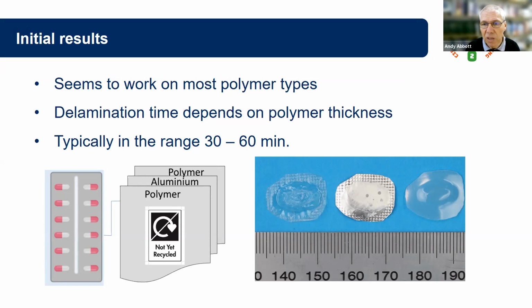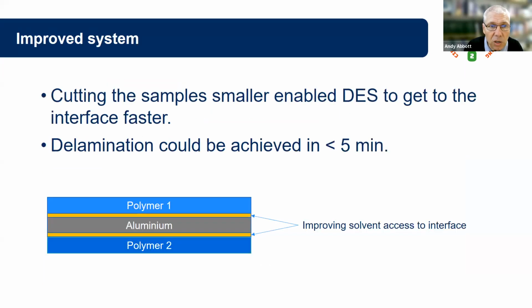We've got a very nice picture on the bottom right of your screen of, I think, a 3-layer multi-package system. Again, this is a blister package that was used for tablets. You can see quite clearly that we've got 3 nice clean layers. Typically this takes between about 30 minutes and an hour to split. That's less than ideal, but it's probably better than anything else out there at the moment. From the photograph, we get 3 very clean layers, which could be very readily recycled as bulk polymers. So we've got a technology that appears to work.